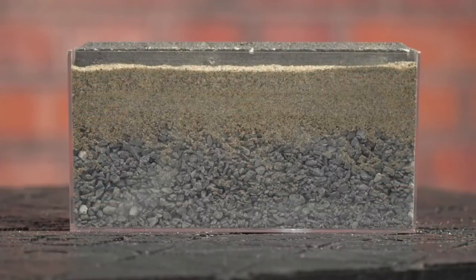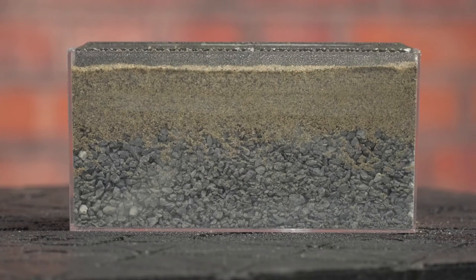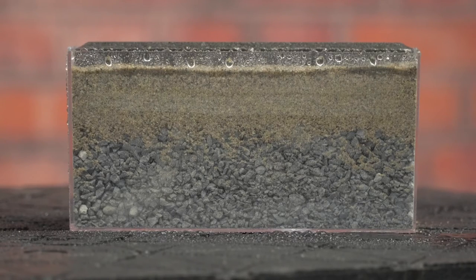Right, so we're going to show you a quick little video here. It shows watering and getting a very thin crust and watering and getting a very thick crust. So here, misting, lightly watering that down. Yep. We're starting to get the polymeric sand activated, right? Right, at the top. But it's only that layer that's wet down that's being activated. And that's what, an eighth of an inch, 3/16 of an inch crust? Yep.